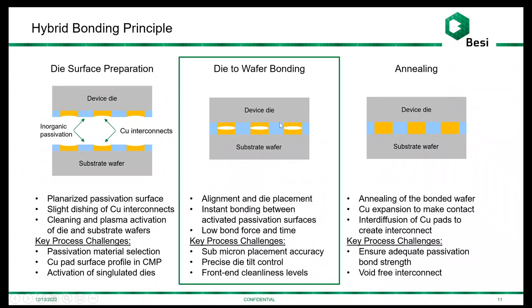But remember, as I said earlier, these are very high modulus, very hard materials. So any small particle that exists in this interface during bonding will actually kill this joint. So we cannot tolerate even a 100 nanometer size particle in this interface. Therefore, the equipment design and the operation of the fab and the integration with the upstream equipment is incredibly critical in order to create a front-end type cleanliness level to achieve this process with high yield.